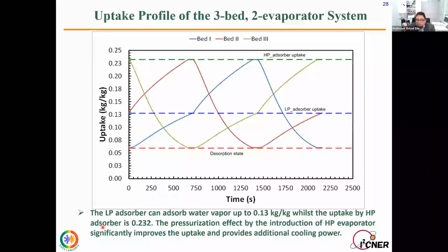So here you can see the low pressure adsorber can adsorb water vapor up to 0.13 kg per kg. That means if you have 1 kilogram of silica gel, it can adsorb 130 grams of moisture, while the uptake by the high pressure adsorber is 0.232. It's much better than the low pressure one because of the temperature and pressure. The pressurization effect from the introduction of the high pressure evaporator significantly improves the uptake and provides additional cooling power. So we can get more cooling power from this high pressure adsorber bed. That is the novelty of this part.